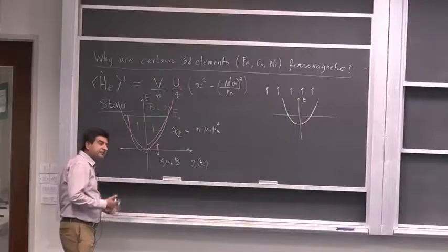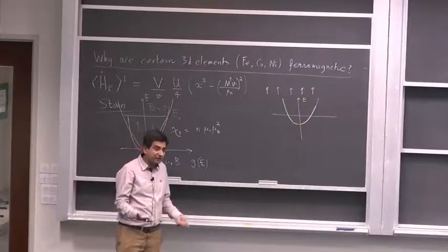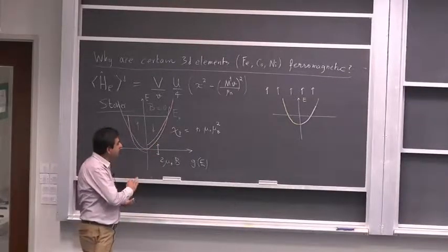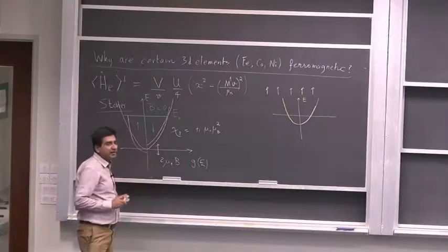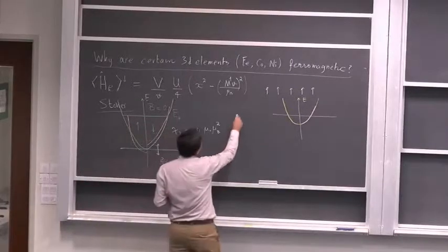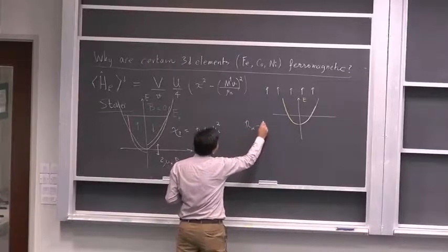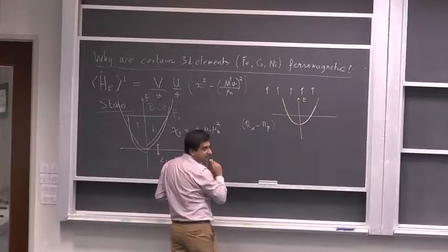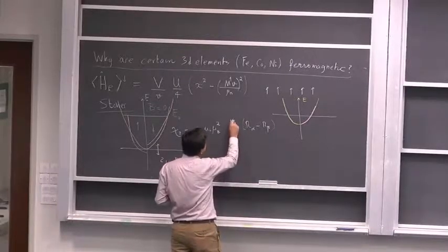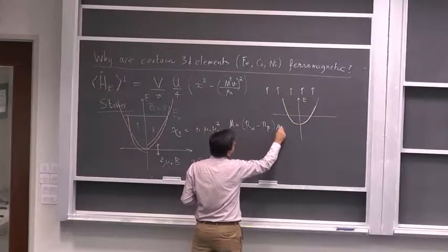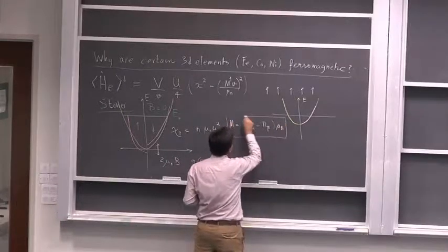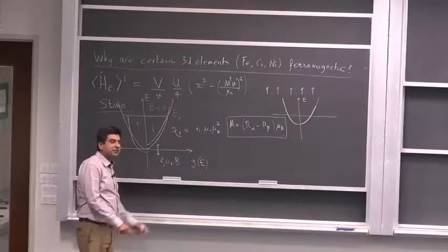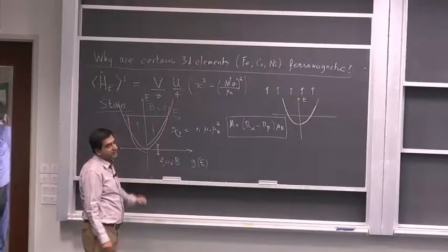But certain materials are spontaneously magnetized, which means they are ferromagnetic. So you don't need to apply an external field. And you get a difference in the spin up and spin down polarizations. Whenever there is a polarization, which means n alpha minus n beta is not equal to 0, you will get some magnetization. The magnetization, of course, is this factor. If I look at spin half electrons only, this is what the magnetization of a material is. So there has to be some polarization difference for a material to have some magnetization.